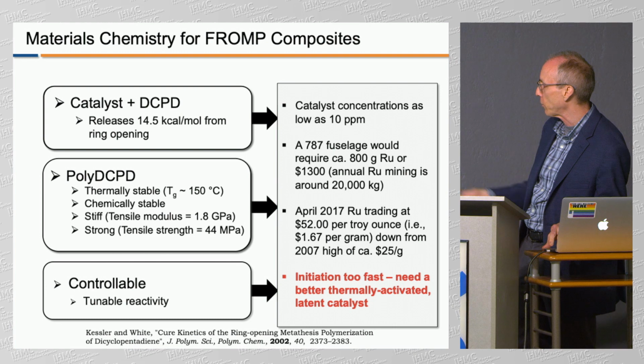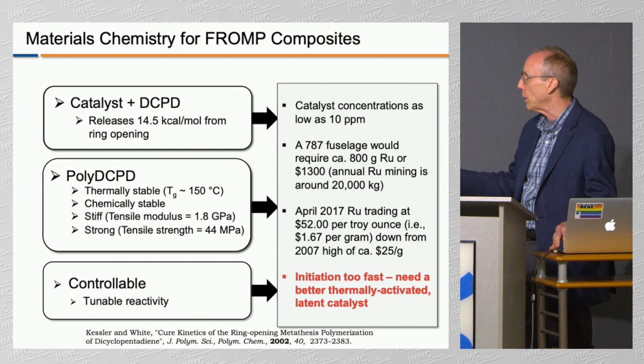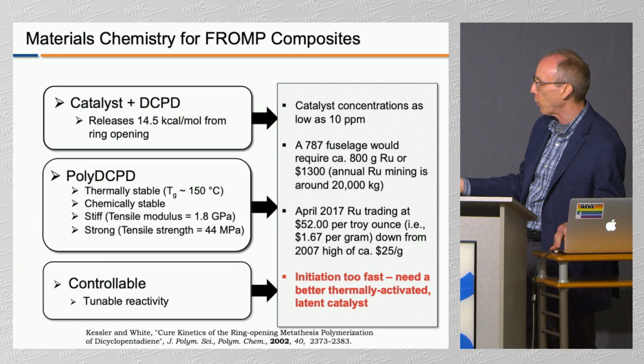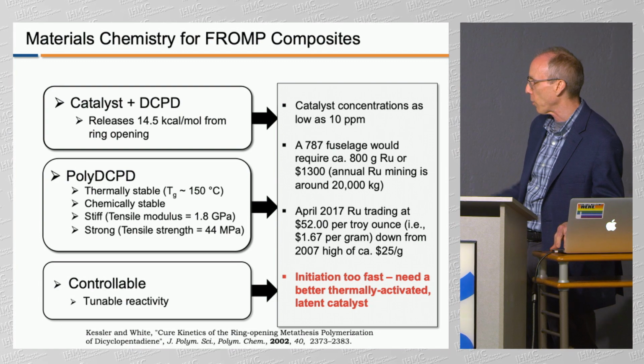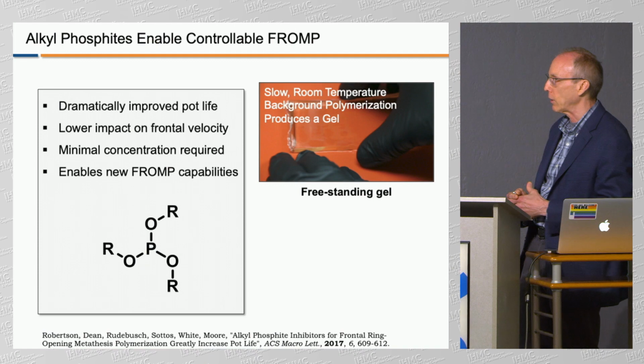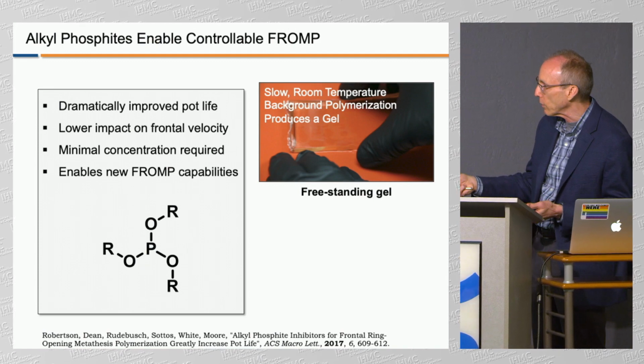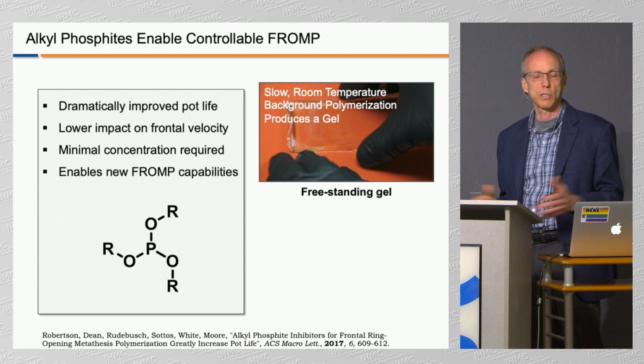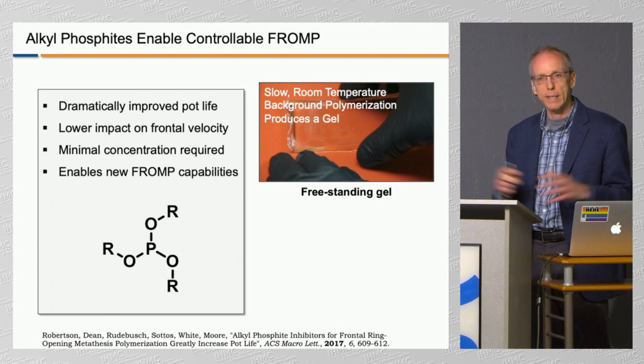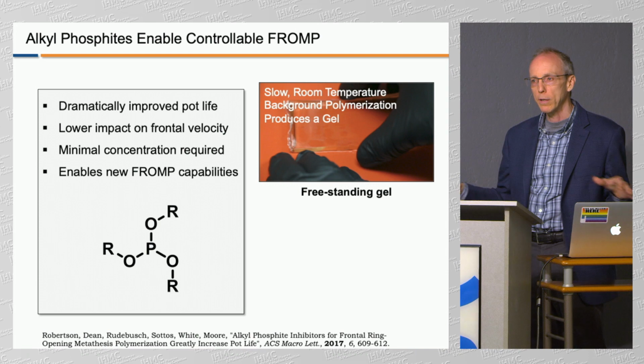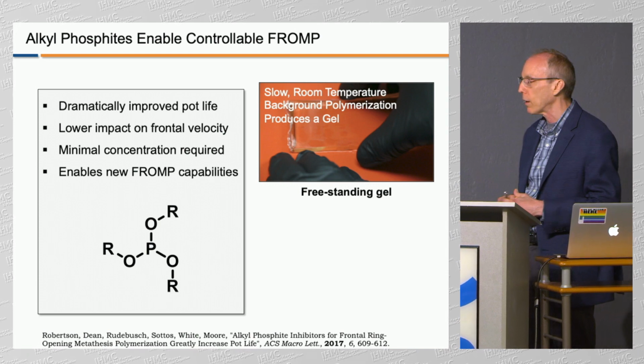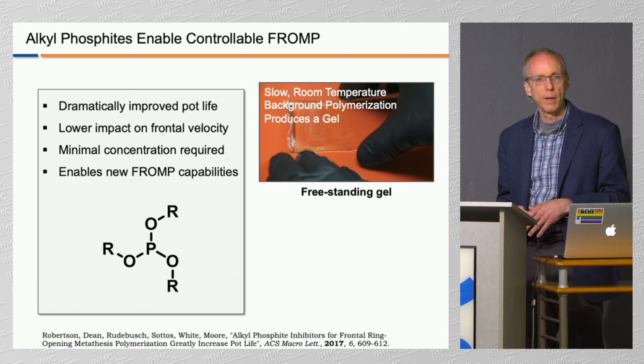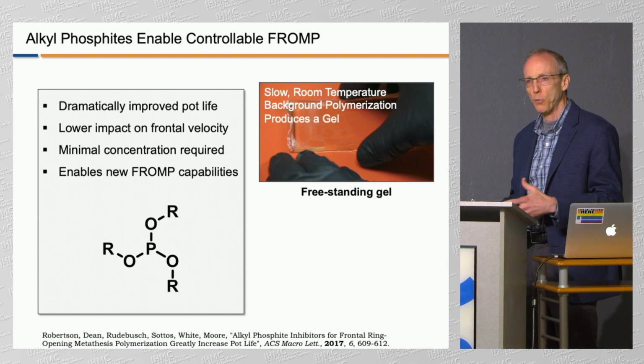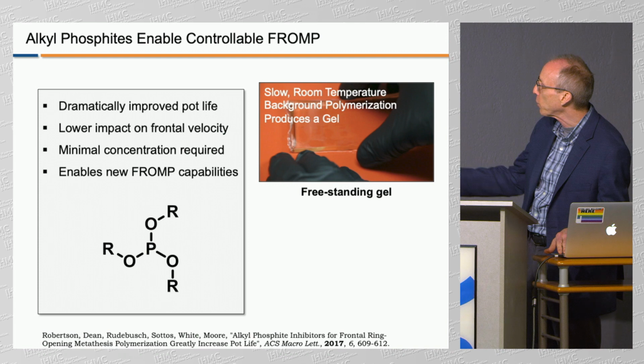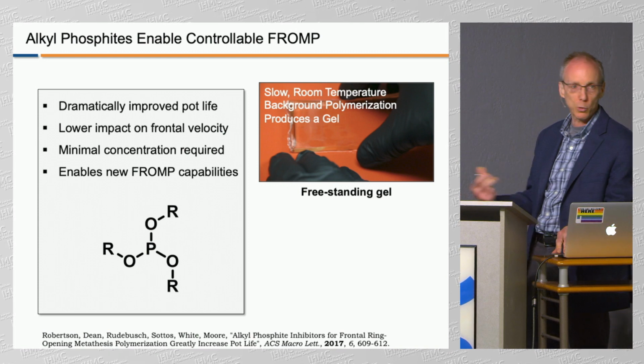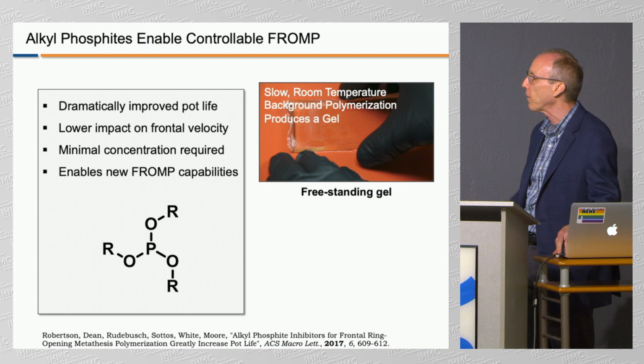The problem is the initiation is too fast. And in general, when you mix that catalyst with that monomer, we need to somehow control it better. And that's where my student, Ian Robertson, came up with this chemical, which really blocked the polymerization at room temperature from taking place. It didn't block it completely. The liquid, that is like water, will polymerize slowly over time. And it's kind of interesting because when it polymerizes slowly over time, it creates a gel-like structure.